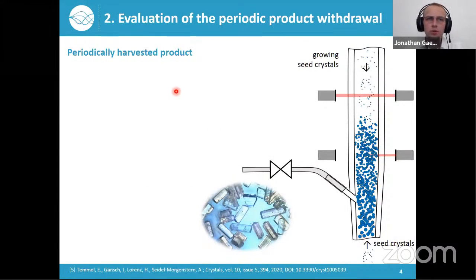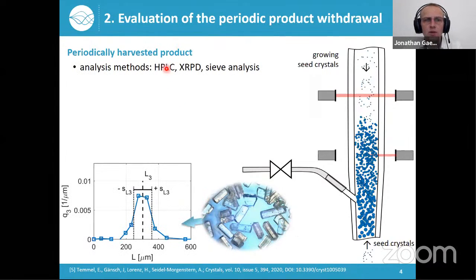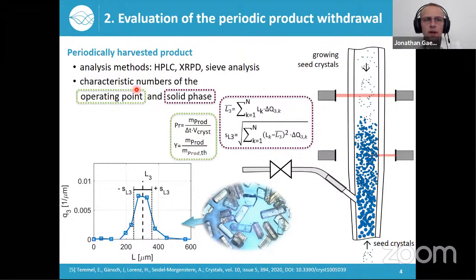To evaluate this continuous process with the periodic product withdrawal, we are using the periodically harvested product crystals. Here you can see an image of our product crystals, and then we do some analysis. We are using HPLC and XRPD to check the purity and also the crystal lattice, and we're also using sieve analysis. Then we define some characteristic numbers of the process. We use the mass of our product, the time window between 2 withdrawals, and also the scale of the crystallizer to define a productivity and the yield. And our product crystal size distribution is represented by the mean crystal size and its respective standard deviation.